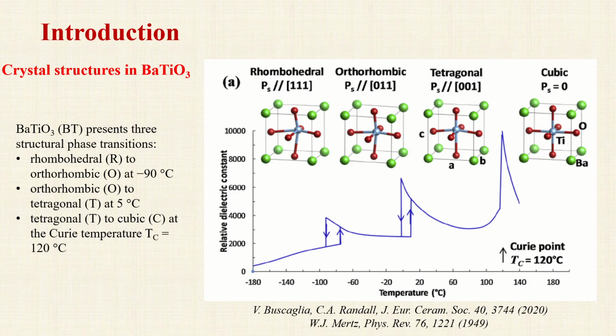Therefore, at some temperatures, barium titanate suffers phase transitions, which are interesting to be studied because they are usually accompanied by enhancements of the functional properties like dielectric constant, as shown in this graph, but also piezoelectric, pyroelectric, electrocaloric, and many other properties. Among the three structural phase transitions, perhaps the most interesting and promising to be studied is the orthorhombic to tetragonal phase transition because it is very close to the room temperature. But unfortunately, we consider that this phase transition is not sufficiently investigated so far.